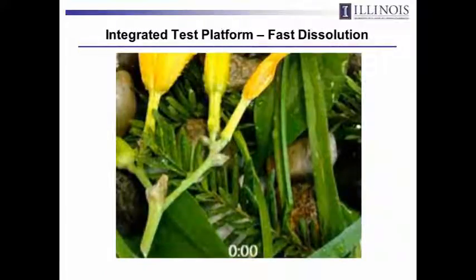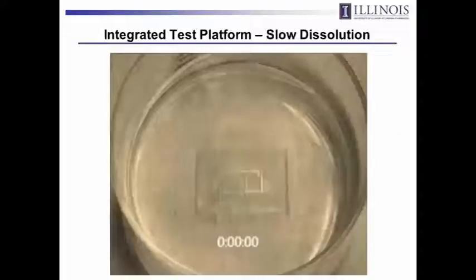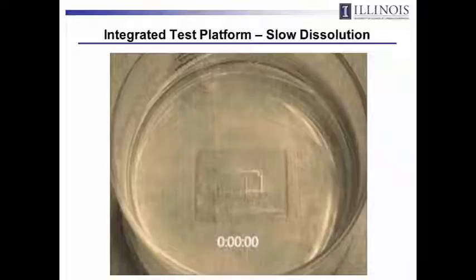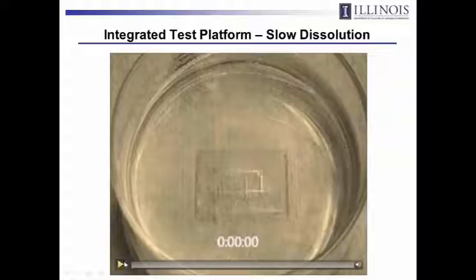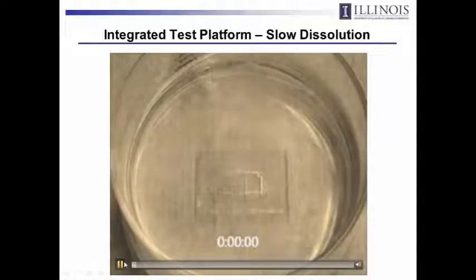So you might wonder, that's awfully quick for a device to disappear. In a lot of cases you want it to last a lot longer than that. And so ways to control the transience time then involve strategic selection of the substrate and the encapsulating layers. So you build in water barriers so that the circuit components themselves are not dissolving away. But those water barriers themselves are slightly soluble, but soluble at a controlled rate. And so once they're dissolved away, then the circuit will start to disappear.